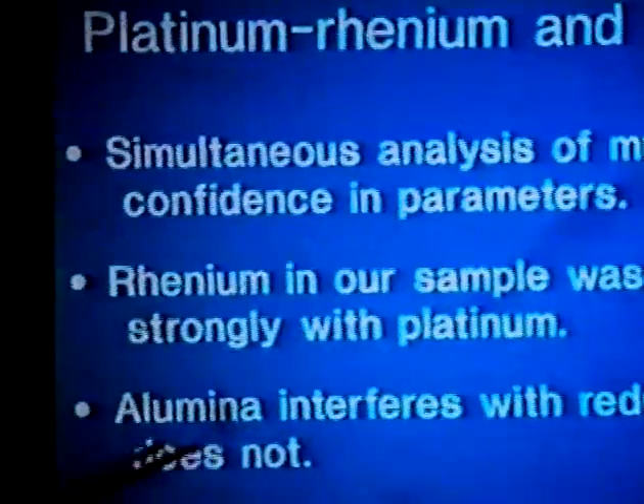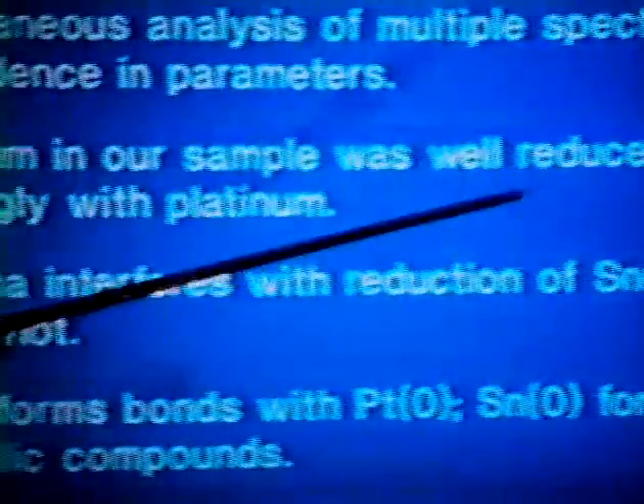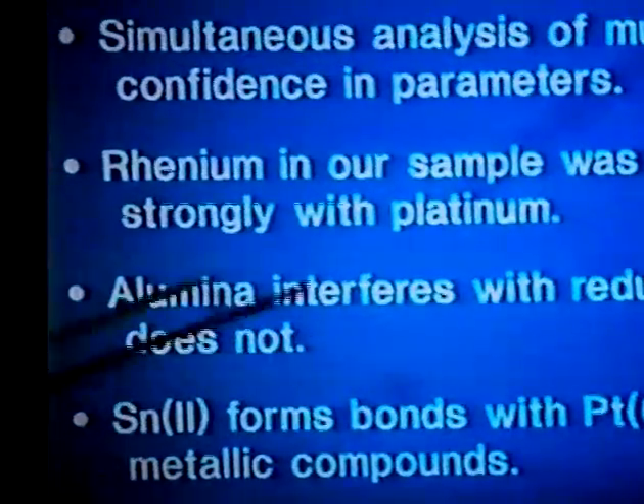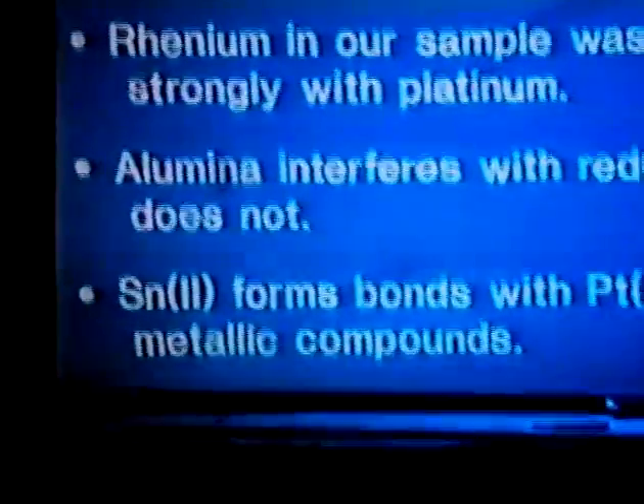If you do an analysis of the spectra with a computer, the computer can insist that the distance or the coordination number you extract from one is equal to the distance or the coordination number you extract from the other. And one of them has one kind of error, another has another kind of error, but the kinds of errors are probably different. And you get some improved confidence. Now, when there are two of the same kinds of spectra, then all you do is reduce the standard deviation in the value of the parameter. Statistically, you get a better number. All right. Rhenium in our catalyst that I've described here was first reduced, and second was interacting strongly with platinum.